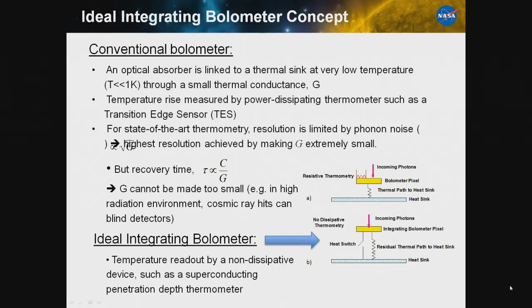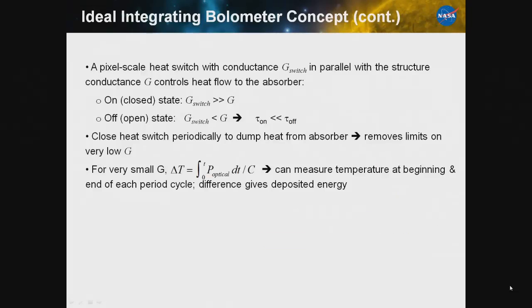So with the ideal integrating bolometer, as I said, we use a non-dissipative thermometer to read out the pixel temperature. And so the power onto the absorber is just the photon power. And we put this heat switch in parallel with the thermal path, with the support structure that's holding the pixel. So we have a pixel scale heat switch, and in its on or closed state, the conductance is much higher than that of the structure. In its off state, it has to be less than the conductance. And so you have two time constants, with your off time constant much larger than your on time constant.